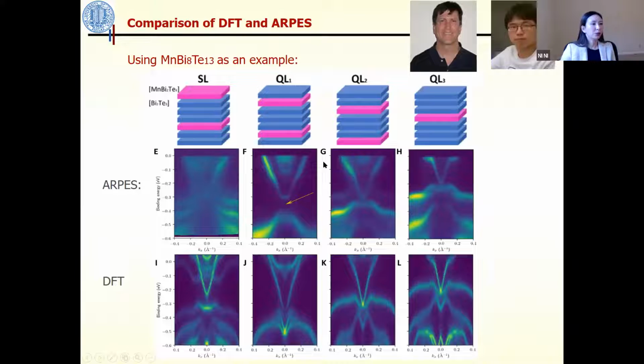This picture shows the comparison between the ARPES measurement and the DFT calculation. When I first got the data, even though I was not an expert on DFT or ARPES, I immediately saw the similarities between the calculation and the experimental data. The agreement between them is just amazing. Look at the lobes and the subtle features. Although the calculated band gap value is smaller than that from the ARPES measurement, it is a well-known problem in the generalized gradient approximation calculation, because usually the GGA calculation will produce a smaller band gap.